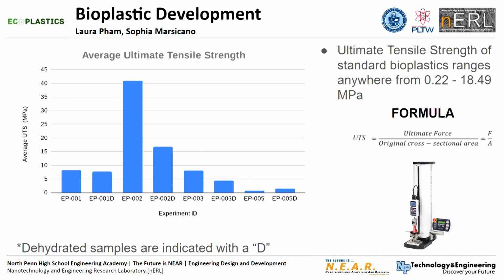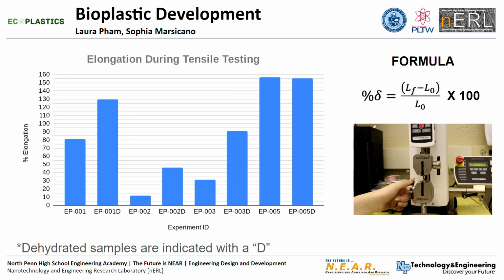As evidenced in this graph, you can see that the highest ultimate tensile strength was achieved by EP-002, followed by EP-002 dehydrated, and our lowest was achieved by EP-005 and EP-005 dehydrated. However, though EP-005 wasn't our strongest, it was definitely our stretchiest, stretching up to 150% its initial length.